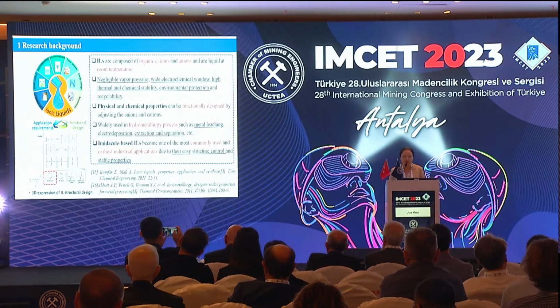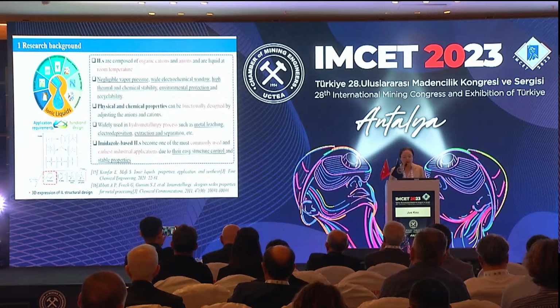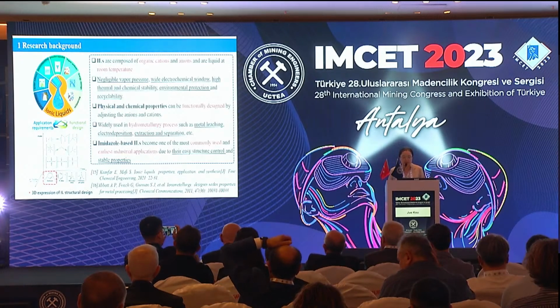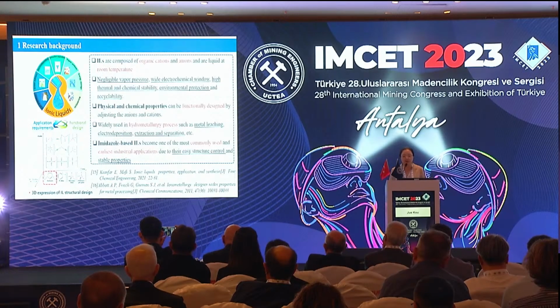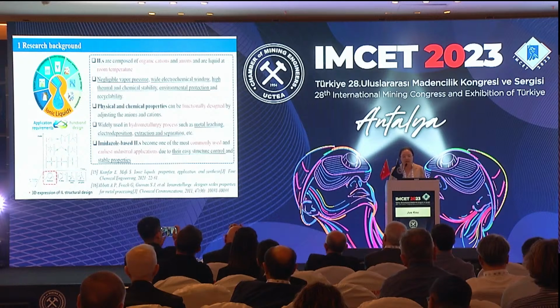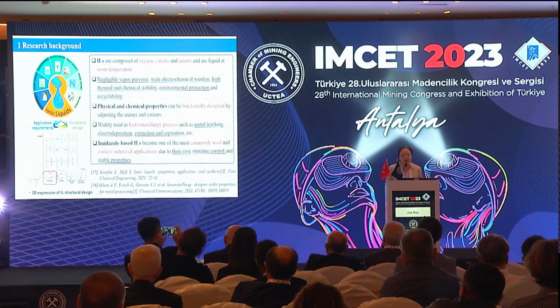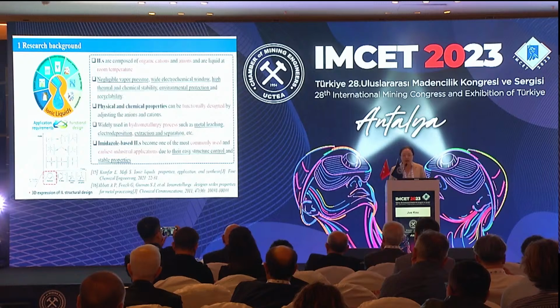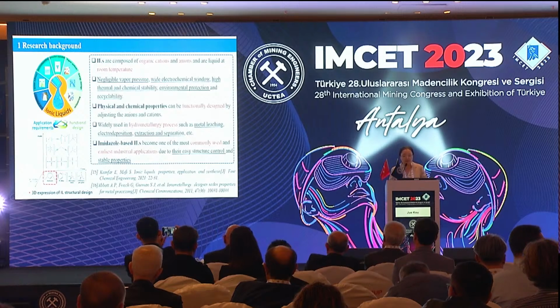And in our research, we are always trying to find some reagents that can provide a stable chemical condition for gold leaching. And ionic liquids can provide a very good leaching performance. Ionic liquid is actually a kind of ionic compound with organic cations and organic anions. Since these cations and anions are quite big, it's a pure component but with a very low melting point. And therefore, this kind of compound is liquid at room temperature. There are lots of advantages of this kind of liquid. For example, it has negligible vapor pressure, a wide electrochemical window, high thermal and chemical stability, is environmentally friendly, and also recyclable. And these physical and chemical properties are exactly what we are looking for in gold leaching, especially the low toxicity leaching.